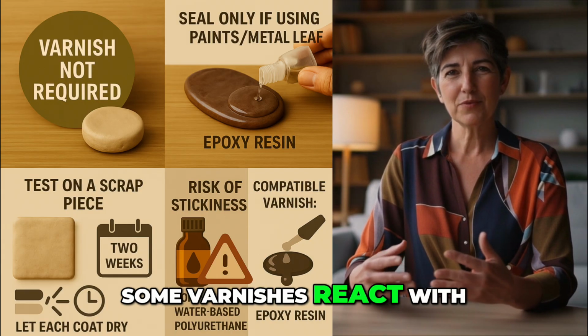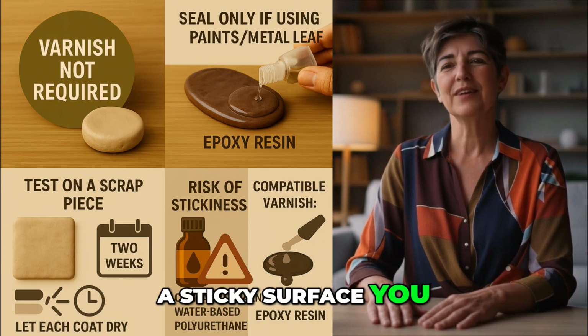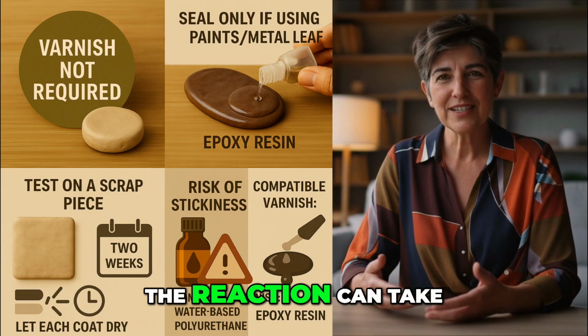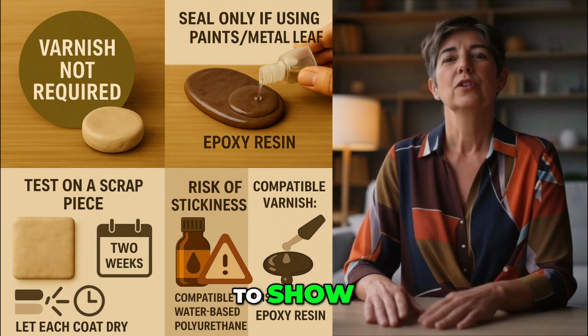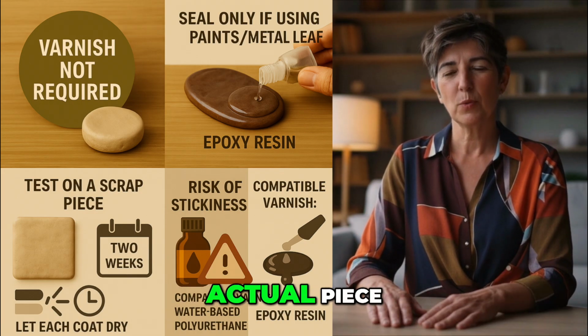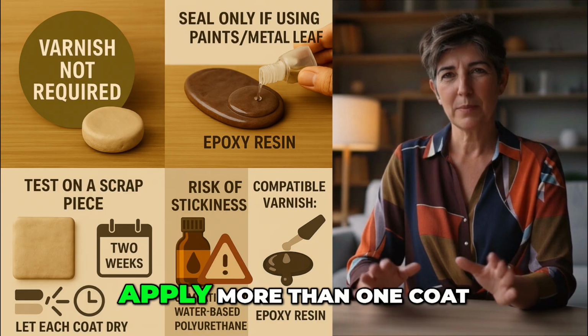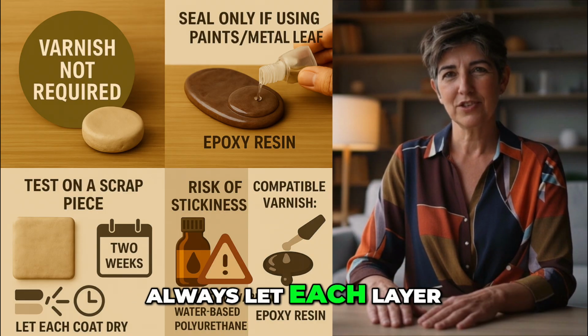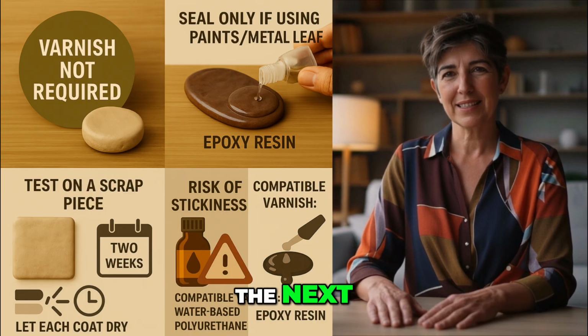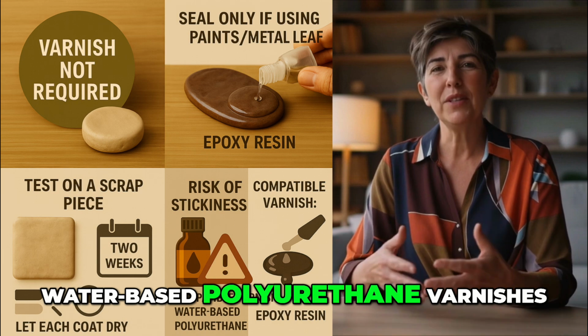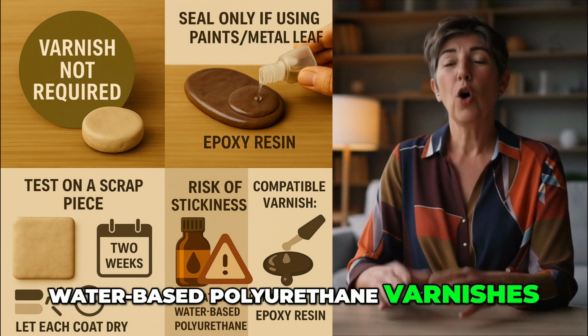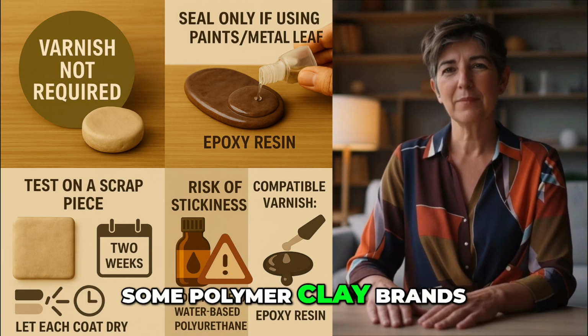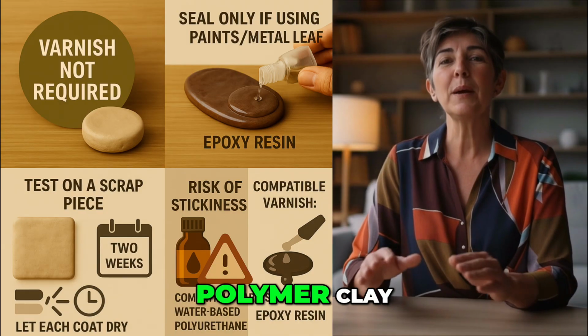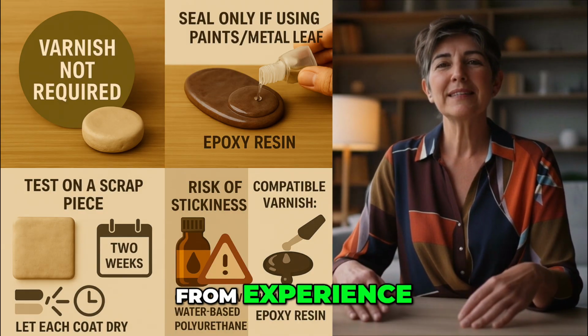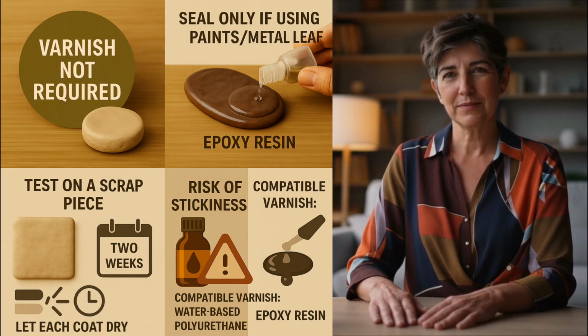Some varnishes react with polymer clay and leave a sticky surface you can't use. The reaction can take up to 2 weeks to show, so give it enough time before coating your actual piece. If you plan to apply more than one coat, always let each layer dry completely before adding the next. Water-based polyurethane varnishes often work well. Some polymer clay brands sell varnishes formulated for polymer clay. From experience, I still recommend testing first.